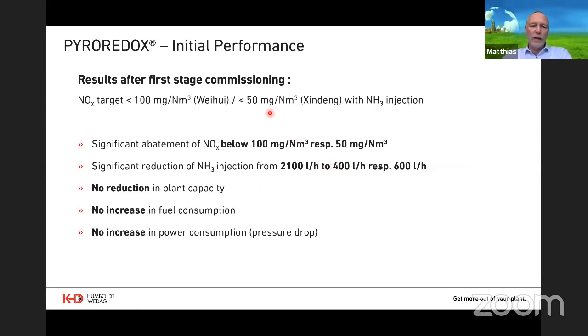We have to get to a limit of below 50 milligrams here. And at the first commissioning, we could already achieve a significant abatement of NOx below 100 milligram per normal cubic meter or 50 milligram. I tell you the numbers in diagrams later on. Also, the ammonia injection was reduced massively, as you can see, and this speaks for itself for the efficiency of this inherent NOx reduction. There was no reduction in plant capacity, there was no increase in fuel consumption, there was no increase in power consumption. That's a huge difference to the SCR technology.